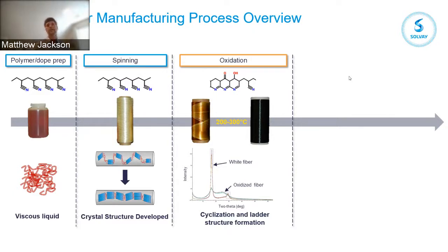PAN is unique in the sense that the temperature at which these cyclization or cross-linking reactions happen is lower than the melting point. A lot of polymers, even polymers with high aromatic content or carbon content, have the fatal flaw of melting before these reactions occur. If you have a fiber that you're putting under tension and it melts in your oven, you no longer have a continuous fiber. And so PAN is really unique in that sense. It's why, even though it was developed around 50 years ago, it's still the primary and prevalent technology used for carbon fiber development today.